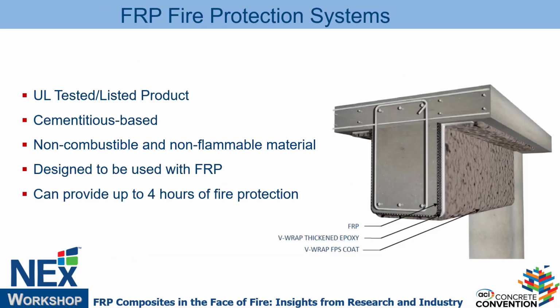Okay, how do I do that? Well, almost all manufacturers of FRP now have a fire protection system that was tested by UL with FRP. This morning, Kodur showed the product that he tested for that. We have a system that we've tested for V-Wrap, Simpson has, Sika has. So it's not something that is not available. It is available and can be used to address the fire rating. It's either cementitious, most of the time spray applied. I think some of it can be troweled on. But the idea is we're using a material that is much lower density, so there's more air in it, more insulation, that's basically going to provide protection.